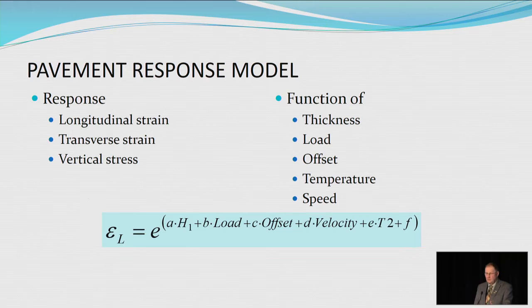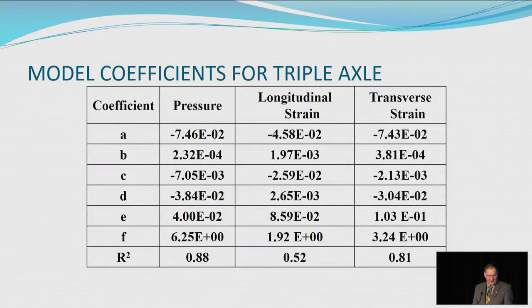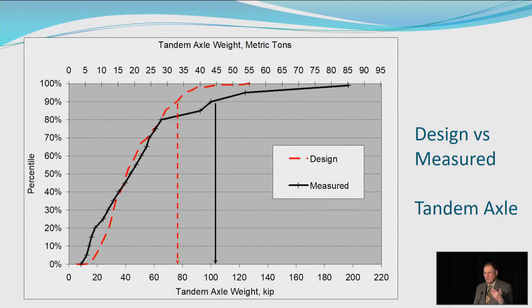Then what we were able to do is to analyze the pavement response and determine the longitudinal strain, transverse strain, and vertical stress on the basis of thickness, load, the offset from where we were, the temperature, and the speed of the vehicle. So we had weigh-in motion, so we had speed distributions of trucks of different weights. There was modeling that was used to fit and come up with a model for those pavements. And then we collected weigh-in motion data for 2 years. And we got distributions of actual weights that were going across.